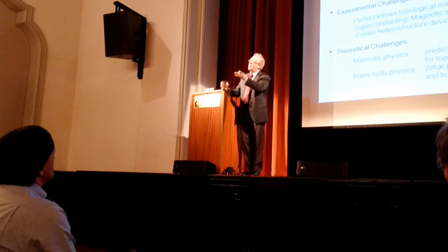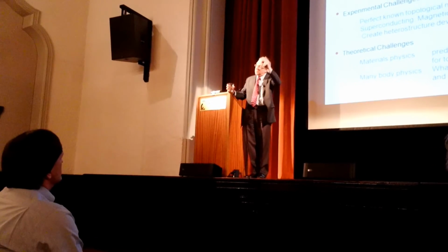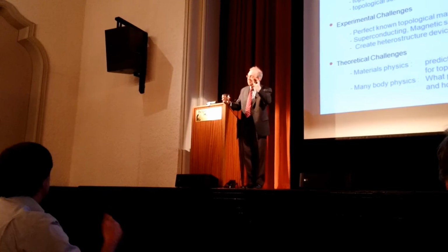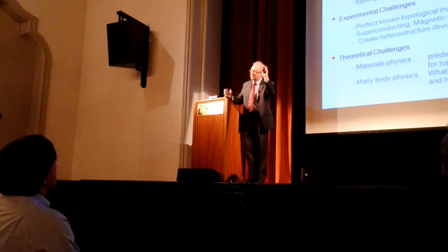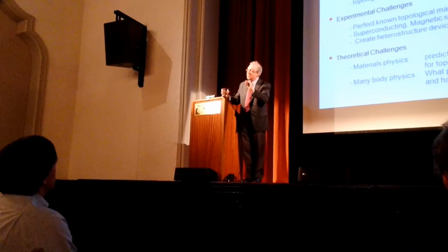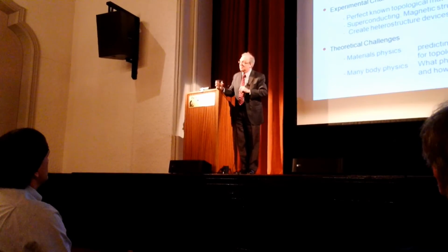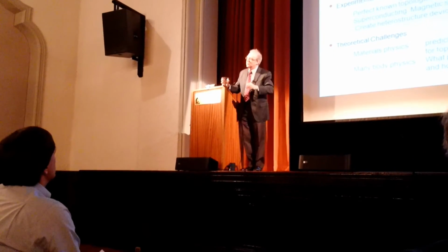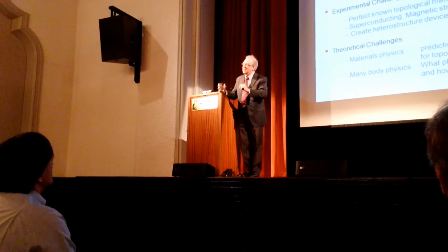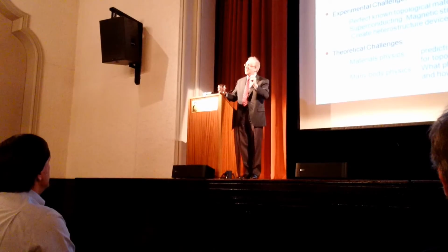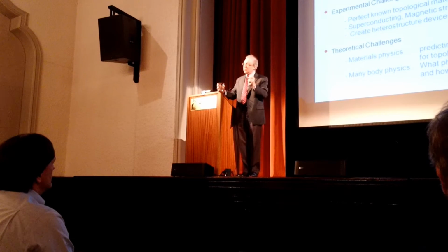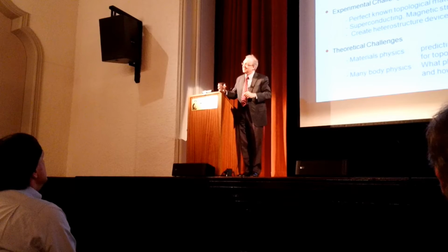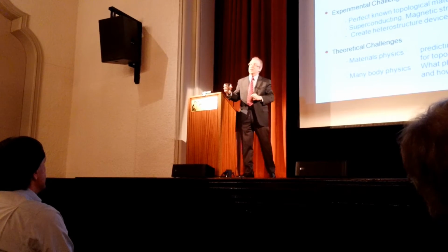Okay. So the classic example is this 1 part in a billion quantization of the quantum Hall effect, which is very well founded experimentally. That occurs in systems that are dirty. Okay, they have lots of impurities. They're not perfect crystals. Okay, and the reason for that is because this state really is a topological state, which is insensitive to changing. Okay, so absolutely it is stable.